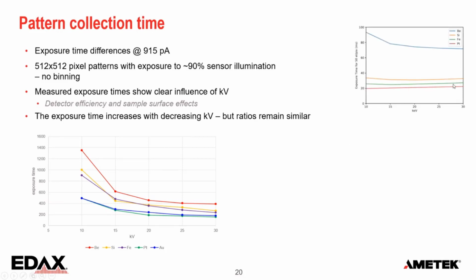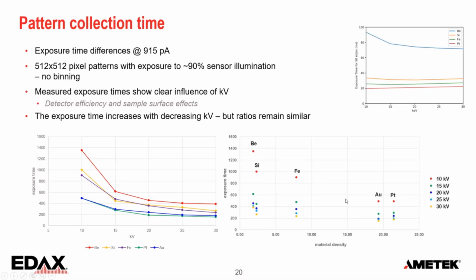Just to compare that with the simulation, it is similar. Beryllium goes up, as we can see here, but the other ones also go up a little bit. And again, that's the sample and detector efficiency. When I calculate that back, not from atomic number, but just on density, then we also see the same effect, and it really shows up or goes up at the lower density materials.